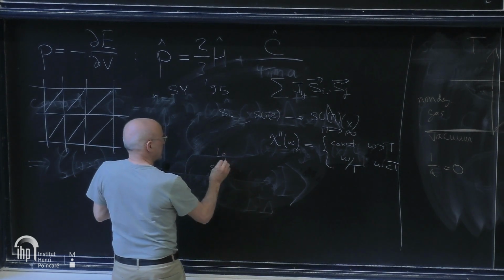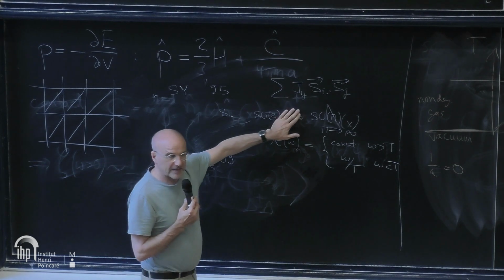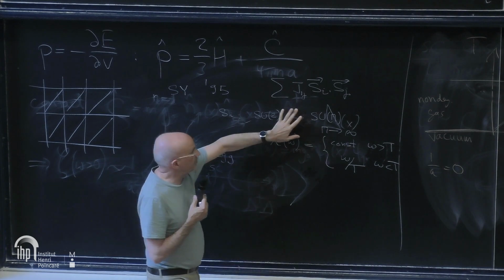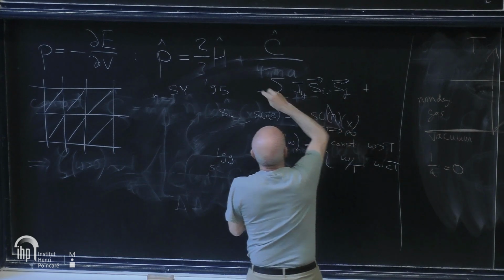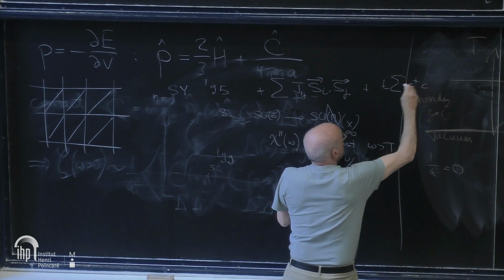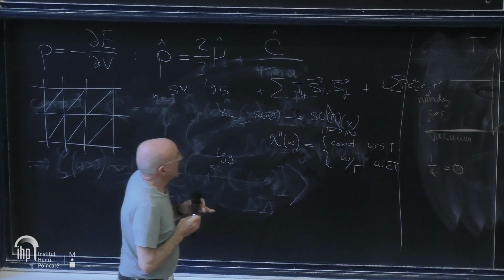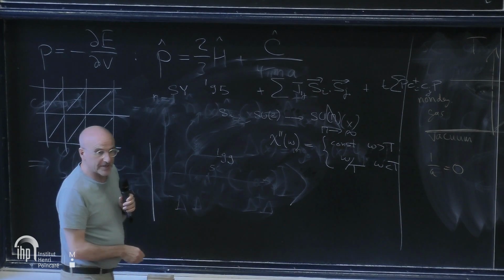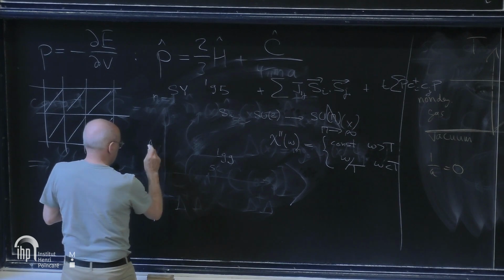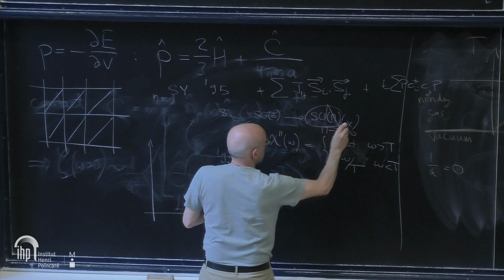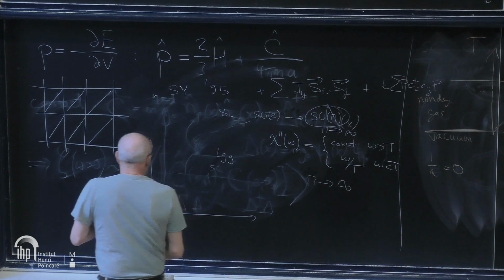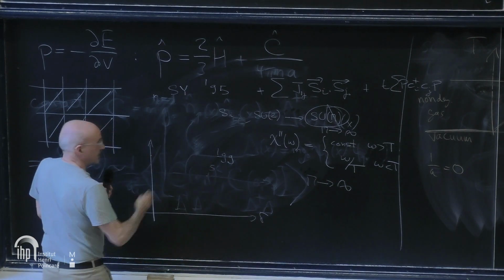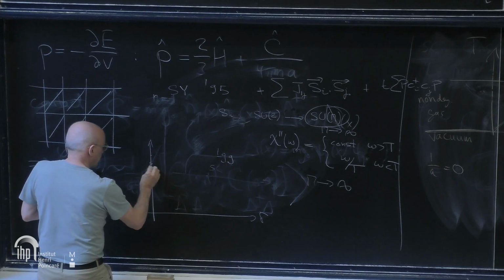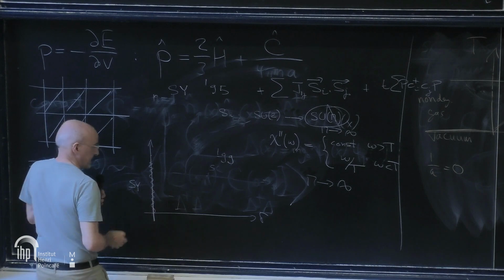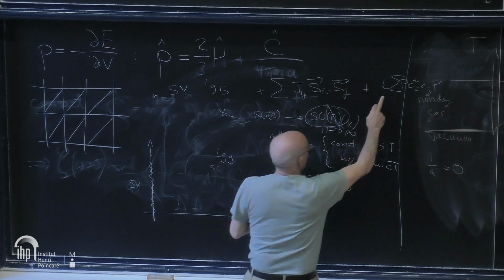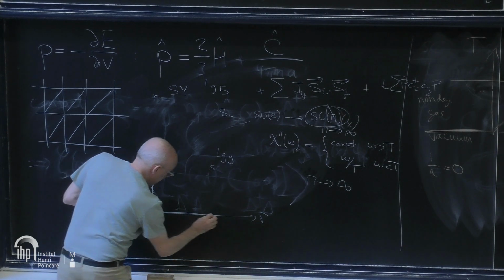So a little bit later, in 1999, Olivier Parcollet and myself actually introduced mobile charge carriers in this system. So we promoted this system to, say, a t-J model, right? Where the particles can now hop with some projector here, right? And what we showed, I'm doing a little history here to explain the train of thought in this field, what we showed, still in the large M limit, so here you have doping, which we can introduce thanks to this t-J extension. Here we have the Sachdev-Ye spin liquid. And what we showed is that this term at zero temperature is a relevant perturbation which immediately stabilizes a Fermi liquid.